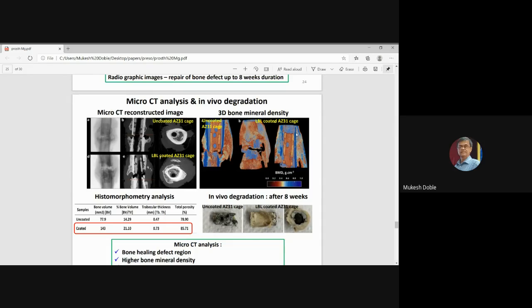Completely healed, actually. The complete defect is filled up. The bone has completely grown. Whereas this is uncoated, you can still see a lot of gaps here. So you can see, again, the coated surface, this is the uncoated surface. So we can compare the bone volume from this picture and this picture. Uncoated after 8 weeks is only 77 cubic millimeters. Okay, that's the bone volume. And here we have 143 cubic millimeters. Almost twice. Percentage bone volume, again, you can see there. And then trabecular thickness is higher. Total porosity also is improved. So the polycaprolactone hydroxyapatite coated magnesium alloy is able to create a lot of new bone and good porous bone.